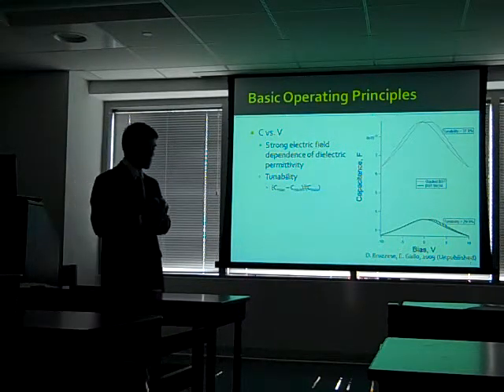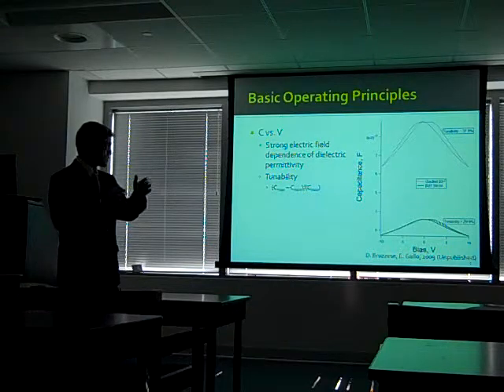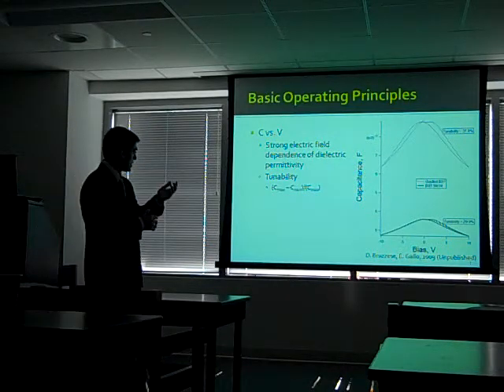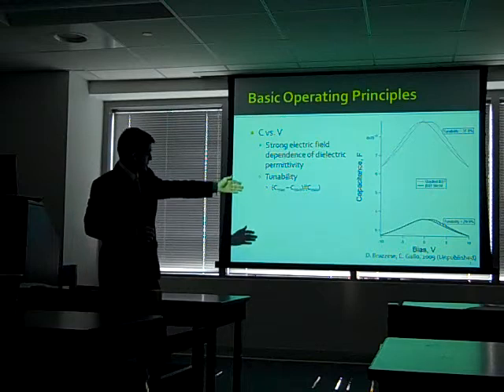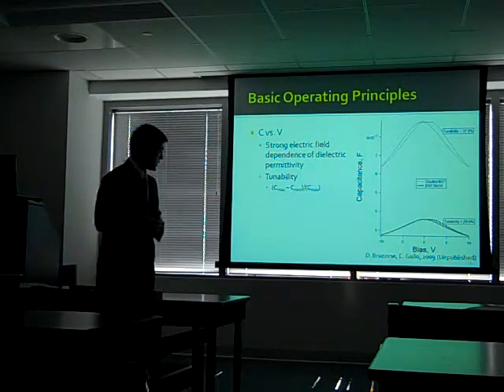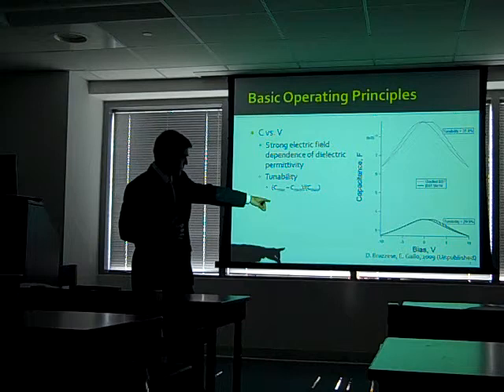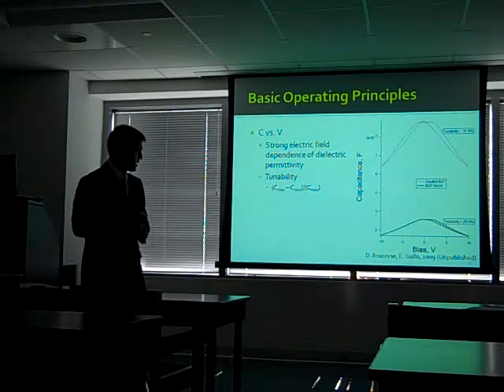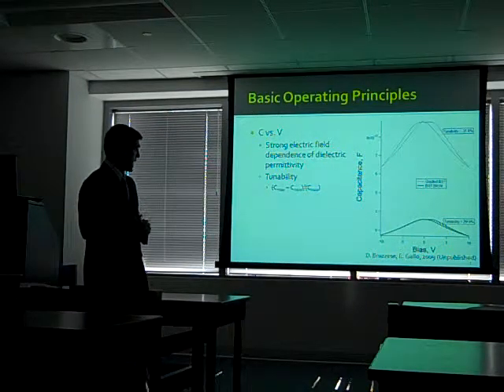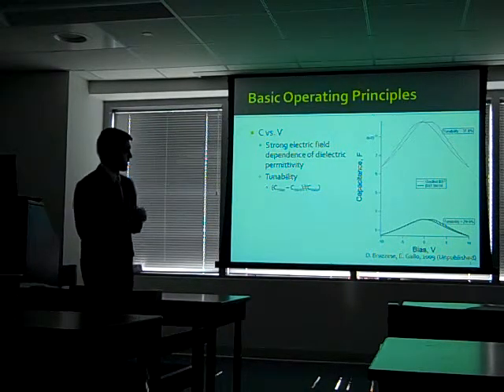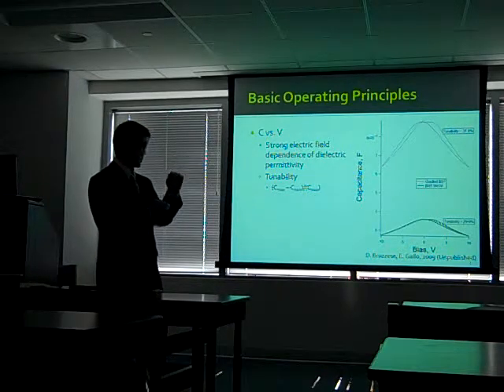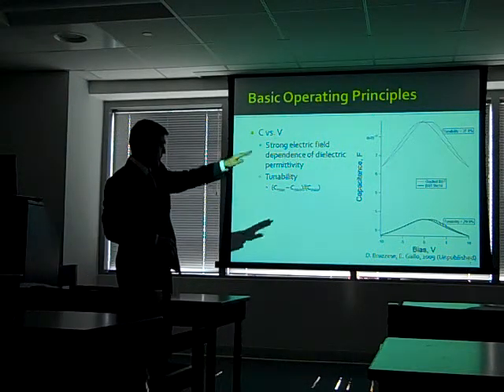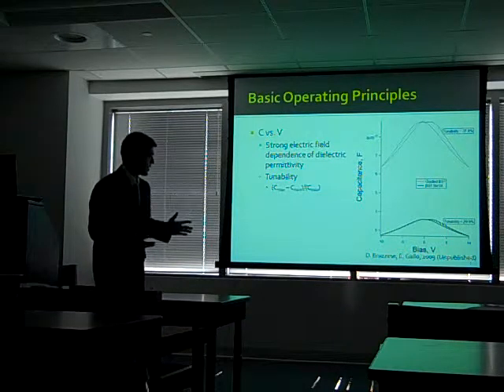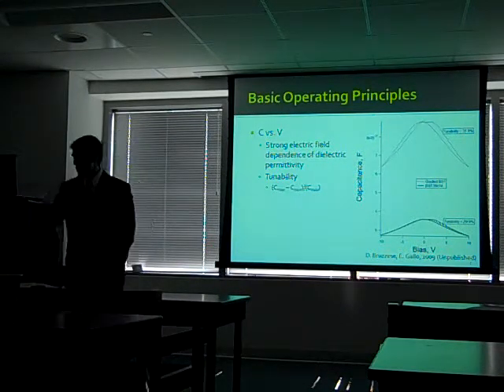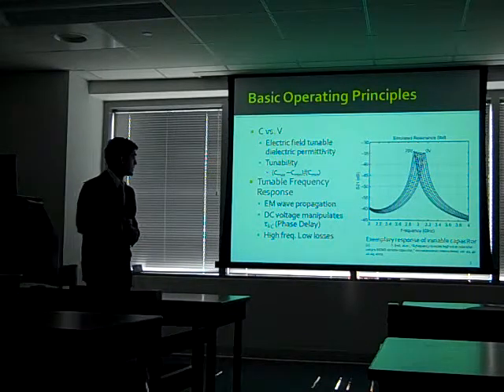Tunability was defined by Dr. Bond and Dr. Alpe as the difference between the maximum and minimum capacitance values divided by the maximum. And you can see here, this is some data that I took with Eric Gallo, my grad mentor. The bottom curve is a single composition ferroelectric film that gave a tunability of about 30%. But the top one is a compositionally graded thin film, so it has 3 different compositions. And you can see a big increase in tunability as well as capacitance overall. So this is one of the reasons we're looking at these.